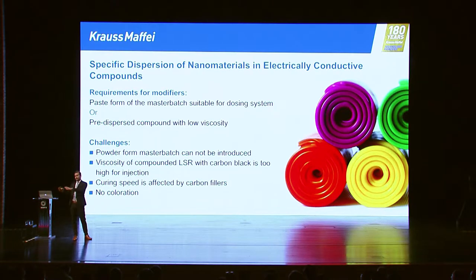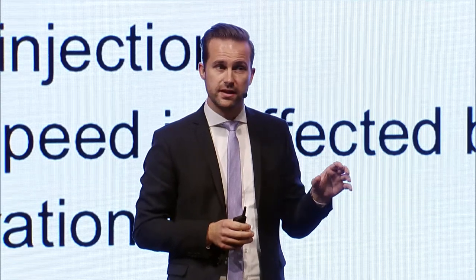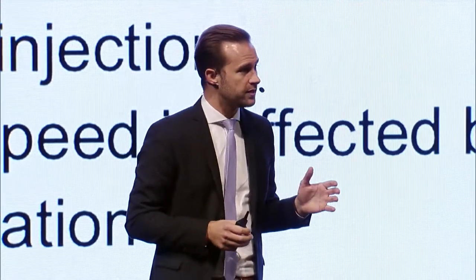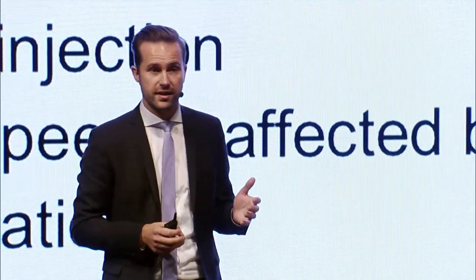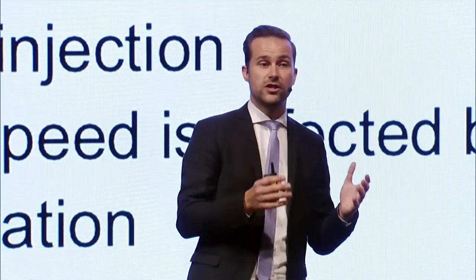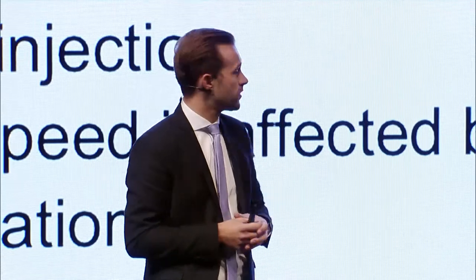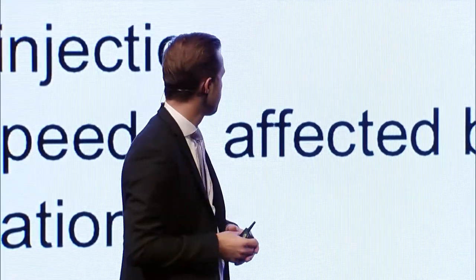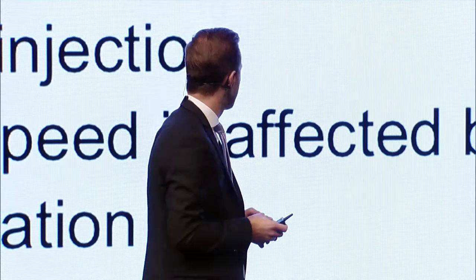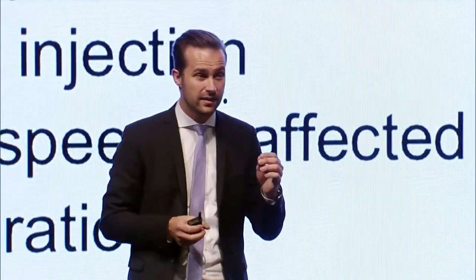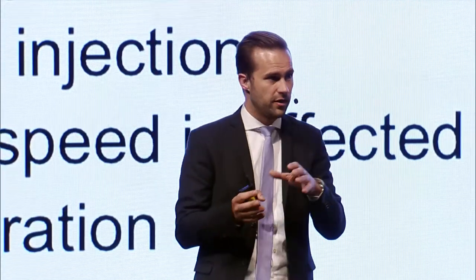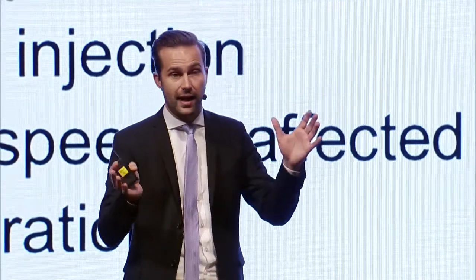But this is only processing. Also inside the cavity, when we need to activate the vulcanization to get the liquid silicone rubber in the end, the curing process of this LSR material is also negatively influenced if you have 30 or 40% of some kind of filler material in there just to get the electrical conductivity. And also, the curing behavior is negatively influenced, and the color. If you put like 30% of foreign material in, your color will not be perfectly blue or black anymore.